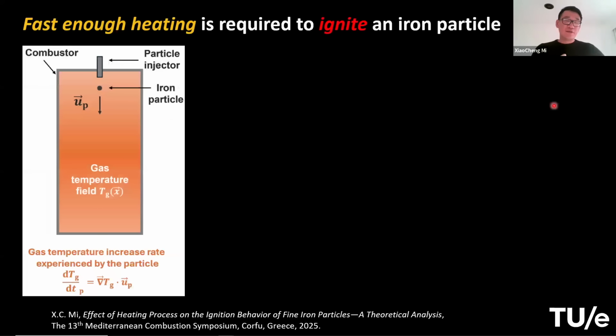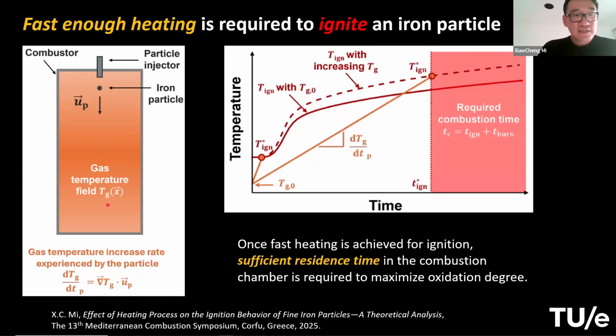And if we take this thought into what happens in a combustion chamber, you inject this particle into this reaction tube. As it falls down, it experiences some temperature gradient, and this will give the particle a temperature change rate as it moves along the combustion chamber. So this is the summary of the graph I showed before. This curve shows the increase of ignition temperature over time as the particle builds up its oxide layer. And this straight line represents the gas temperature change rate experienced by the particle. A steeper slope means faster heating, and a shallower slope means slower heating.